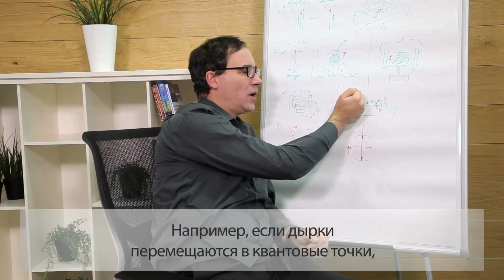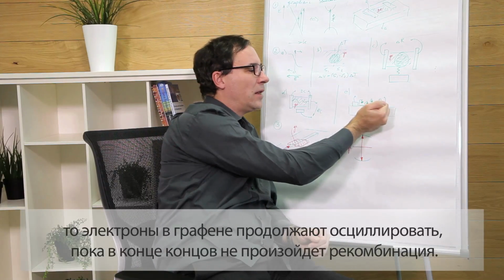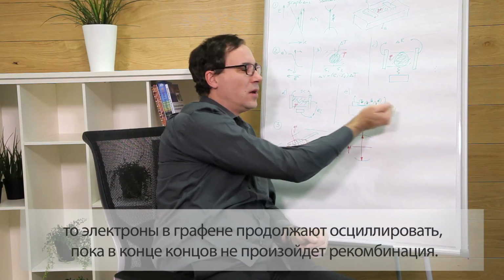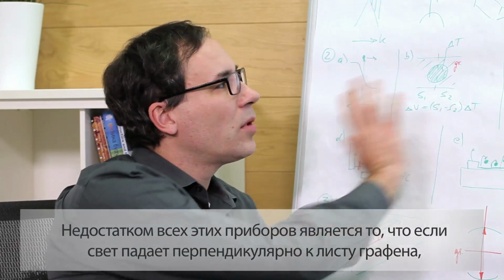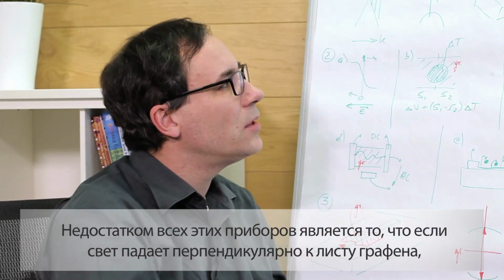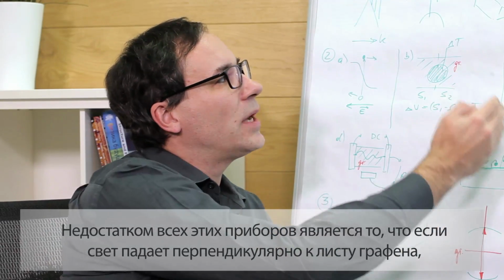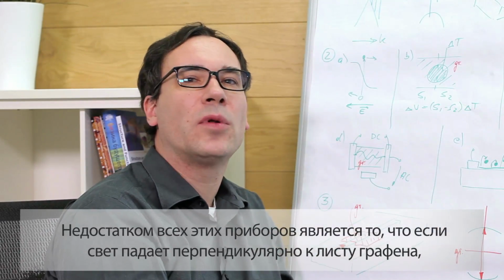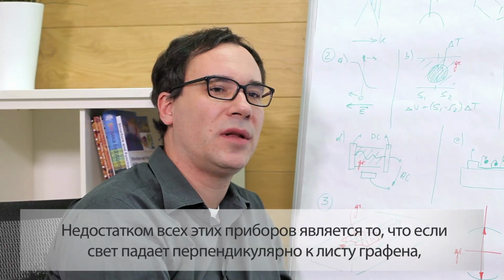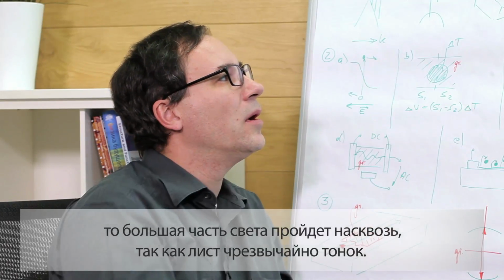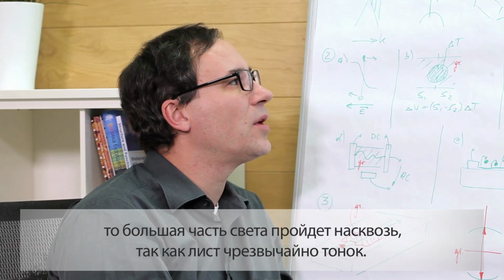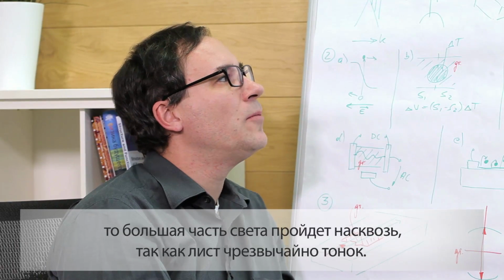And for example, if the holes are transferred into the quantum dots, the electrons in graphene keep oscillating until eventually they recombine. So it gives you a very strong photoconductive gain. It's actually a very sensitive kind of photodetector. Now the drawback of this device in general is that if you shine light in normal incidence, most of the light would be transmitted through your device, because the graphene sheet is extremely thin.